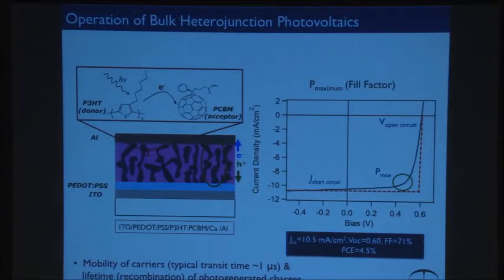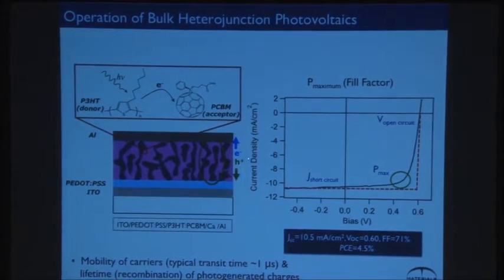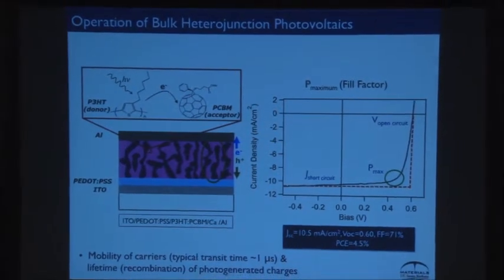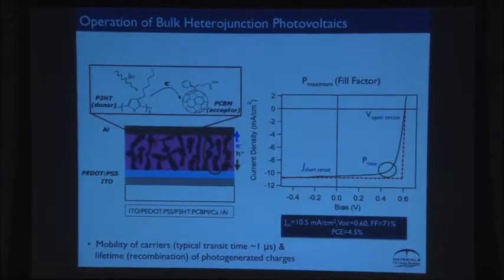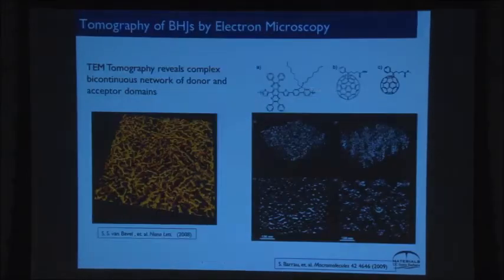Okay? Now, what sets this point? If I have a big electric field between the electrodes, as I am here, it's very easy to pull the charges out. If I'm actually here, as I move this way, the electric field across the device is decreasing. And so what that means is the transit time for the electron and the hole to get out is increasing. And as the time is increasing, they have more time to recombine. And so this point is basically a trade-off. It's related to the transport, how long you can keep these carriers alive and how long it takes them to get to the electrodes. Okay? And typically the fill factor is the most difficult thing to control and understand.